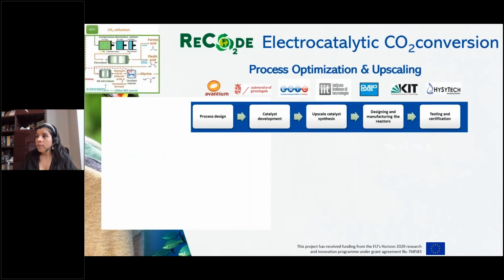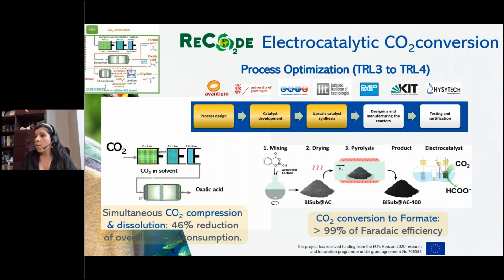Regarding the electrocatalytic conversion, we have also passed through a process of optimization and scaling up. So we have first developed a CO2 simultaneous compression and dissolution system in order to enhance the energy efficiency of the dissolution of the CO2 in the liquid electrolyte.